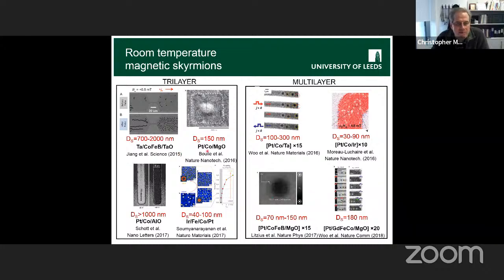So you can have this tri-layer where you have a ferromagnet with something above and below it, or you can take a whole stack of those tri-layers and pile them up into a multi-layer, and there are examples of that on the right here. And you can see these skyrmions can be pretty small. These are the biggest on a sort of micron scale, but more often you're down in the hundreds or even tens of nanometer range. And I think the smallest that's been seen to date is a little more than 10 nanometers, at least at room temperature. You can do fancy things at very low temperatures.